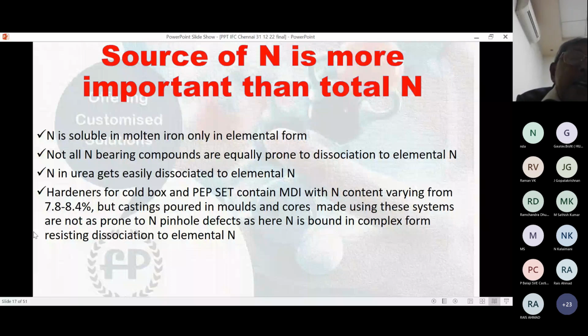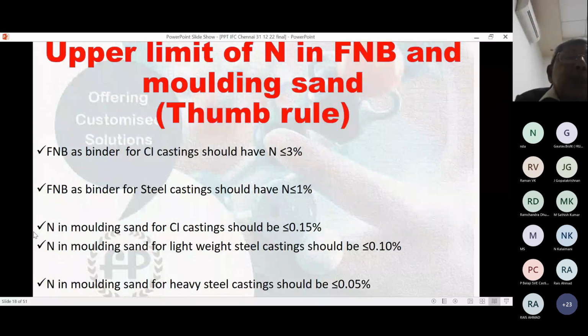For example, hardeners for cold box and PEP set contain MDI, where nitrogen content varies from 7.8-8.4%, and it is added at 0.8 to 1% by weight of sand. But castings produced in molds and cores made using these systems are not as prone to nitrogen pinhole defects, as here nitrogen is bound in complex form resisting dissociation to elemental nitrogen. So this is the limit of nitrogen. It is a thumb rule and book values. Furan as binder for cast iron casting should have nitrogen less than 3%. Furan as binder for steel casting should have nitrogen less than 1%.